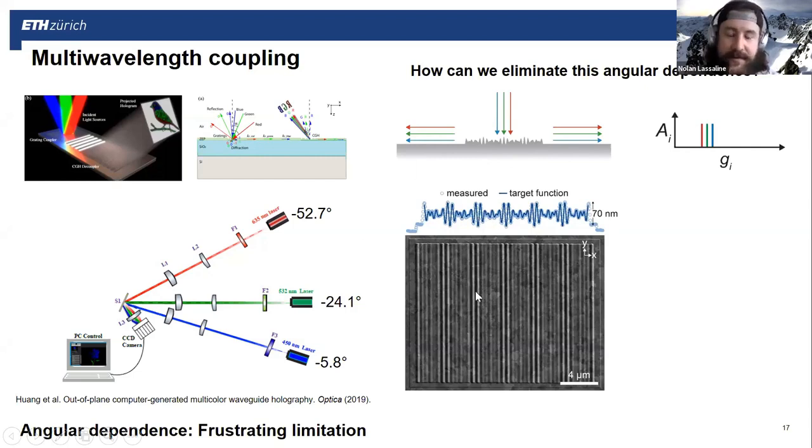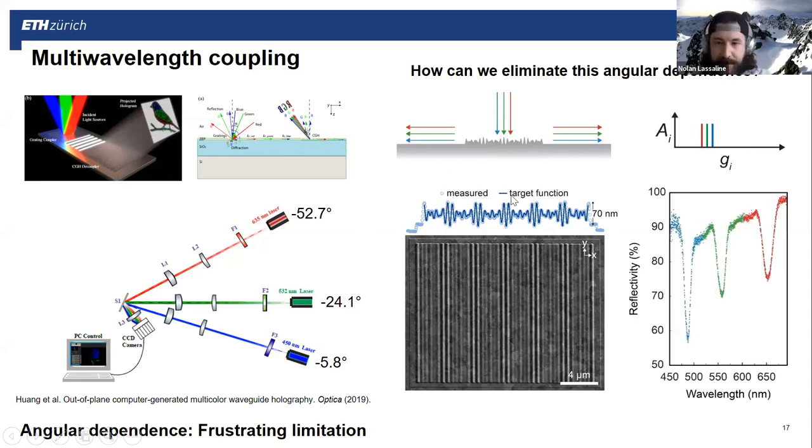And we can transfer this, of course, again to silver. And when we shine light on the surface, what we very nicely see is that this surface is able to simultaneously couple the 3 colors we want, red, green, and blue, shown here nicely with this optical data and their 3 corresponding peaks. And the take-home message there is not only that we made such a surface that can couple multiple wavelengths, but it's really a demonstration of how this approach is not only very simple, but also very powerful, that you can really use it to precisely solve these diffractive problems that you may want to do.